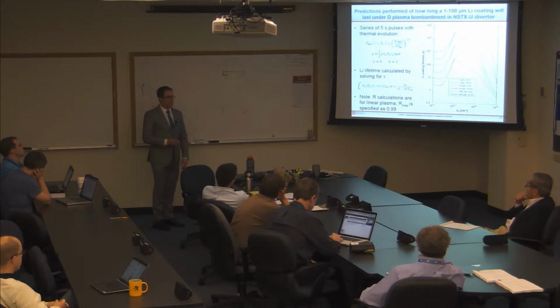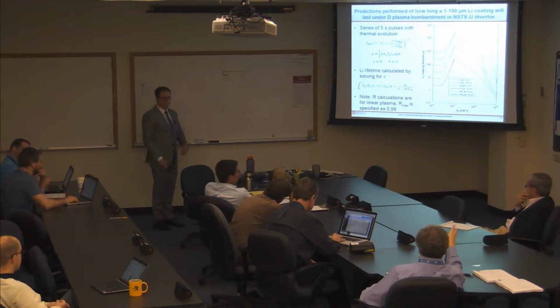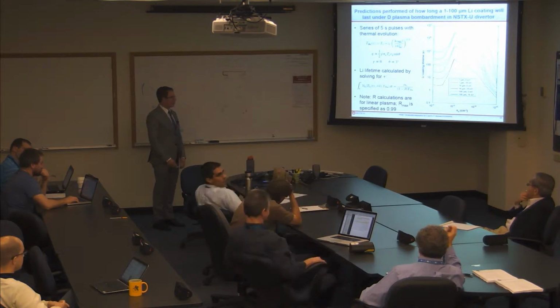Well, I'm varying them both because I plotted two different electron temperatures, 5 eV and 10 eV. And then that CS is obviously related to those. So essentially what's happening is the heat flux is going up by orders of magnitude as we go along. Yeah, the heat flux is changing.